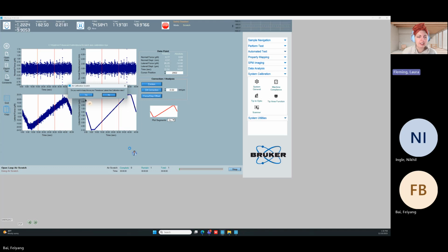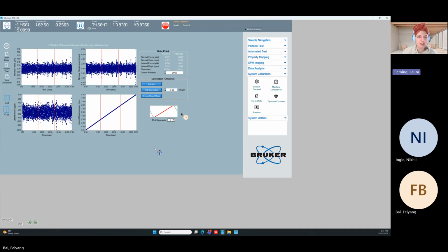So we're going to go ahead and click yes here, and it's going to take this center part of the lateral force and calibrate that to 0. When we do so, a couple things change. You see now from this screen, we only have this segment selected. So we're going from 8 seconds to 38 seconds here. That's that center scratch from -5 to +5, which we can also see in this lateral displacement here. How we judge the calibration is based off of the lateral force. What we typically like to see is it's centered around 0 and the spread be roughly 10 micronewtons or below. It looks like that's mostly true here. We're offset a little bit. That's pretty typical when the transducer first goes into scratch mode. You're turning on a bunch of circuit boards.